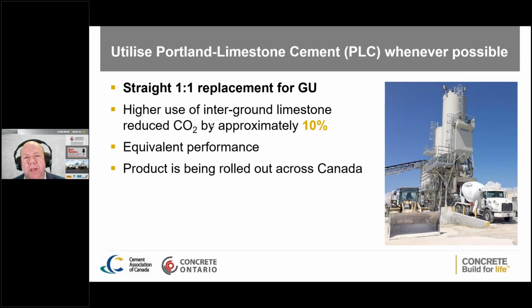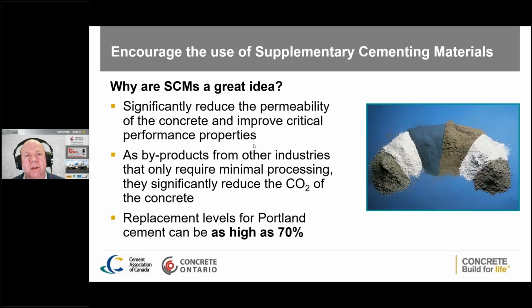Other key component, we've been talking about Portland limestone cement here in Ontario for about 10 years now. Usage is very significant now. I think we're one of the leaders in the country in use of Portland limestone cement. We won't get into the cement chemistry here, but basically we've got an elevated amount of limestone in the cement. The cement is processed at the cement plant to a finer particle size that makes it more reactive. We get the exact same concrete performance when it comes to strength development, air entrainment, freeze-thaw resistance, permeability reduction with this material for a 10% carbon reduction. So again, for the concrete industry, it's basically a one-to-one replacement. Whatever your GU content was, you're going to replace it with GUL and see that 8 to 10% carbon reduction right off the bat. So there's a lot of opportunities there.